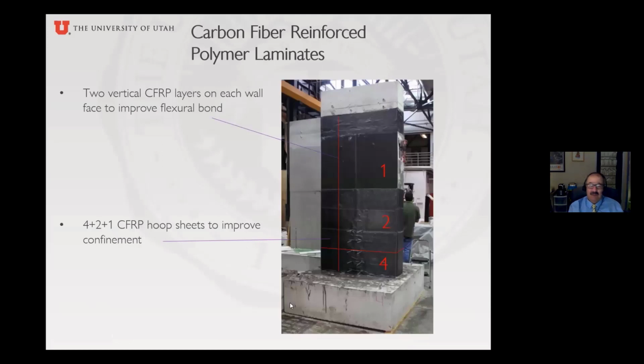So here is some picture that shows the bottom 4 layers of confinement, then this area with 2 layers, then the one area with 1 layer. And of course, you also see the 1 layer which is vertical for improving the flexural capacity.